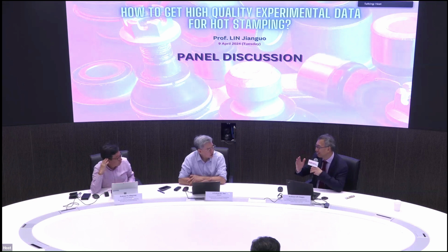That's it. We only model this, and we can't get it exactly, because different locations have got different cooling rates. Because the cold die contacts some areas, cooling very quickly. Some areas have not been in contact with the die. The cooling rates are lower. We try to control the lowest cooling rates to be above the critical cooling rates. We only control that one.